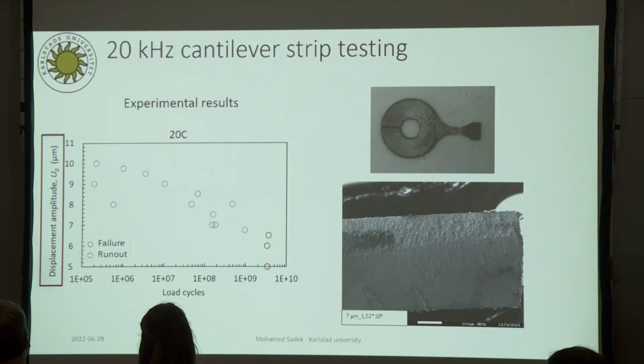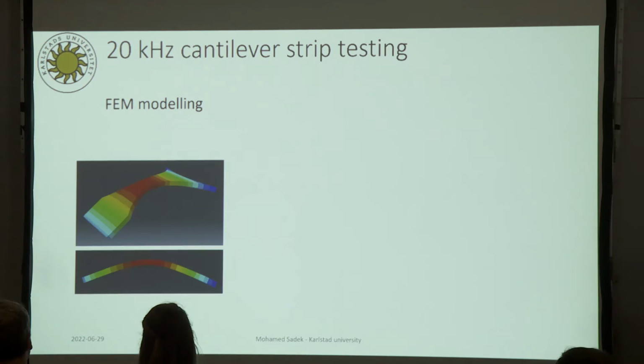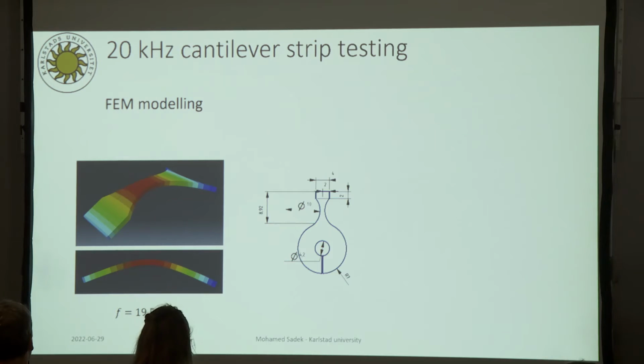We do that, of course, by FEM modeling, and this is what I will start talking about now. We start by trying to design the specimen, to find the right dimensions in order for it to have a 20 kHz frequency. This is actually what we started with, and we found these dimensions for a frequency that is within the range. Then we ordered specimens with this geometry and tested them, and we got all the results that you saw before.